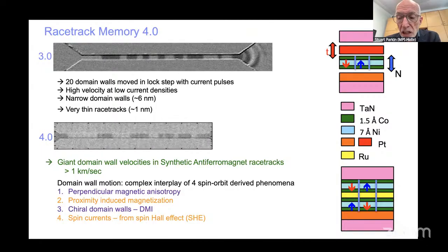Ruthenium is a very special case. When ruthenium is very, very thin, the coupling is anti-ferromagnetic. When you increase the ruthenium thickness, the coupling between two successive magnetic layers sandwiched by ruthenium becomes ferromagnetic, and then becomes anti-ferromagnetic again with thicker ruthenium, with a period of approximately 10 angstroms. This is something I demonstrated in 1990, 1991, and this is true for nearly all transition metals and noble metals. This enables us to build very interesting synthetic anti-ferromagnetic structures such as this one.